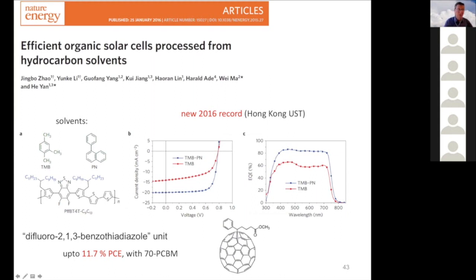And they used what they call a green solvent. They used this phenyl naphthalene, a very weird solvent, but it's not very volatile. So in that respect, you can imagine that they call it green. Here you see the IV curve. So again, you see that using phenyl naphthalene as the co-solvent, as some extra solvent, you can generate much more current in such a cell compared to the other benzene solvent. And also the external quantum efficiency, so basically how many photons are converted into electrons. Also that curve is much higher at every wavelength that is absorbed. So you can understand that the phenyl naphthalene co-solvent has a very good effect.